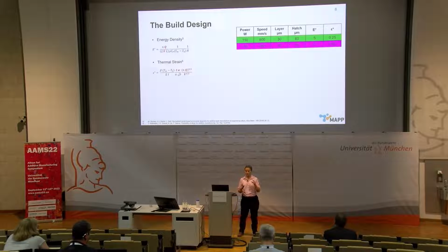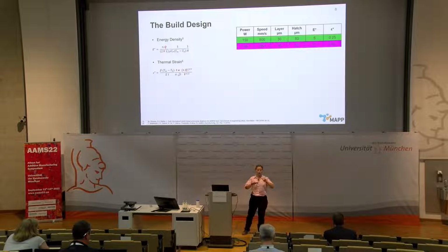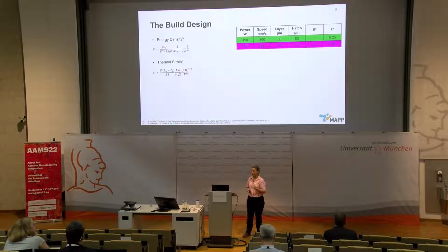So we can see there's a lot of overlap between energy density and thermal strain, but they're not identical. And we can play tunes with the scan velocity to affect how those balance out, and we can play tunes with the melt pool length and that characteristic time. So there's a lot of ways of tuning these two parameters against each other. We've started off with two different build parameters.